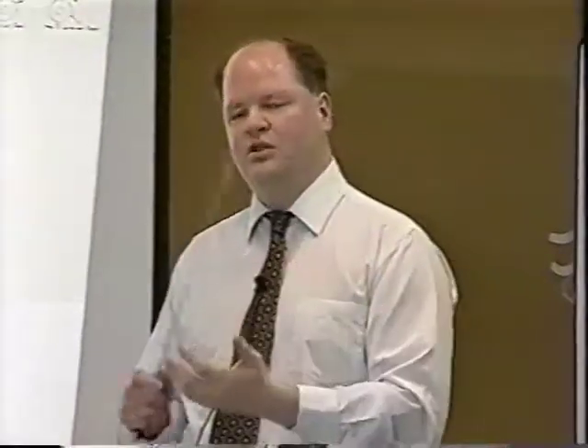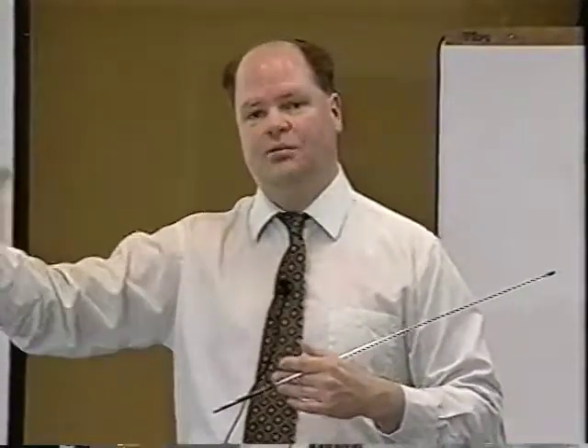If we produced a non-IF steel off our hot dip line, we don't have, let me see how to explain this, because I'm not a metallurgist. When Pete was talking about the CHTL line this morning, how it had that overage section on there, that was to eliminate the yield point elongation from returning through that strain aging. Our hot dip line anneal furnace does not have that overage section. If our hot dip line did have that overage section, we could run IF or non-IF, it wouldn't matter. Since we don't have it, we're kind of limited to running IF, so we don't get that yield point elongation returning, or the strain hardening returning.